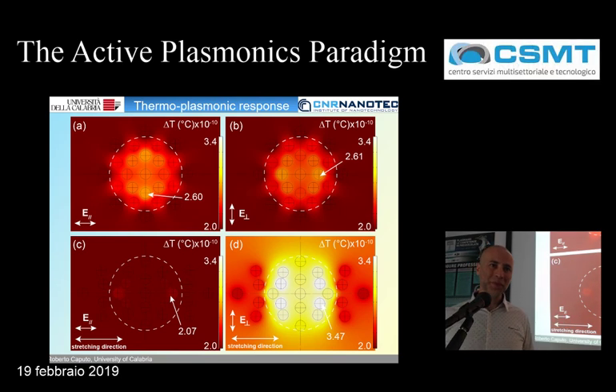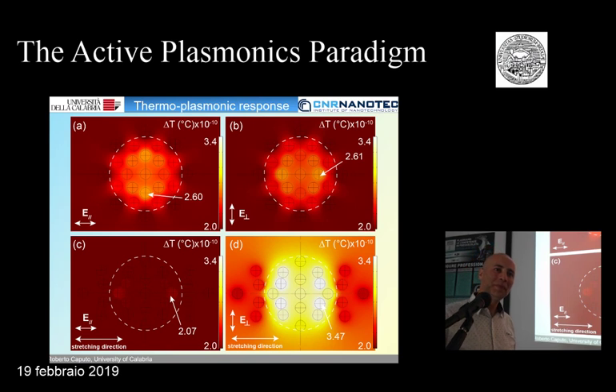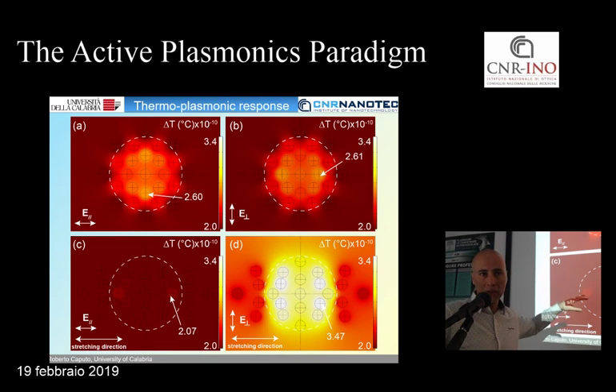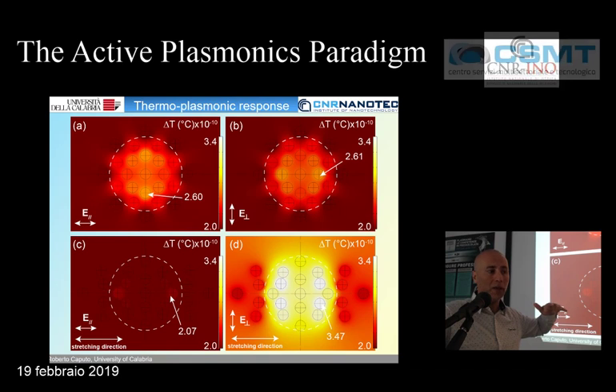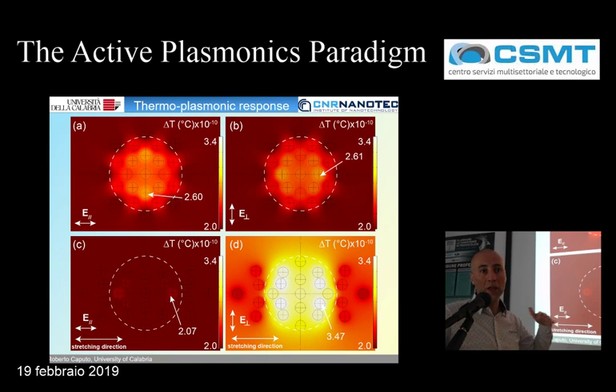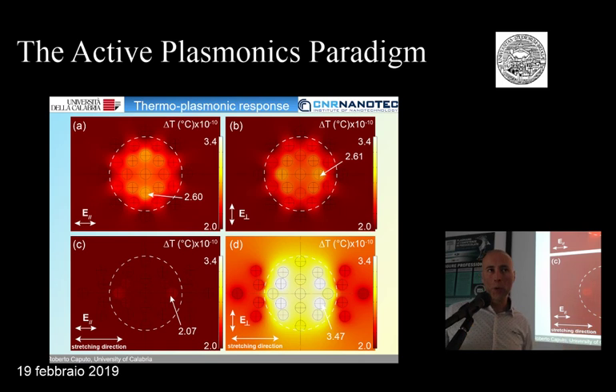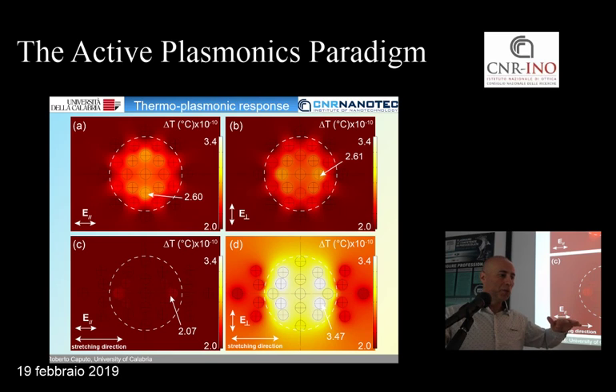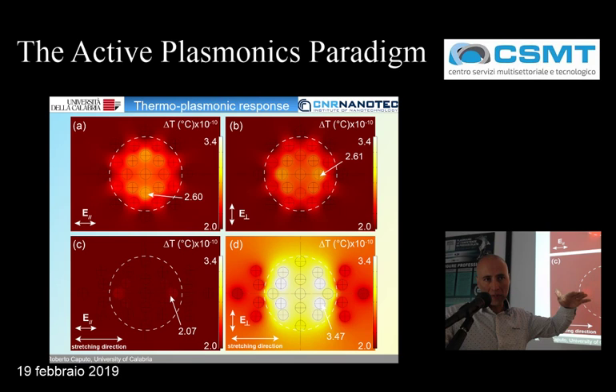Thank you. I am very curious about the increase in temperature you can get. Is there any possibility to increase this range? Okay, there are many ways to do this. In principle, by keeping the same particles, you could increase the pumping intensity. So you modify what I called an offset temperature, and then you can play around it by simply stretching the sample. So if you need a larger tunability range in temperature, in that case, I think we should change the particles. But if you need, for example, to pass instead of from 40 to 50, from 70 to 80, this could be the way.